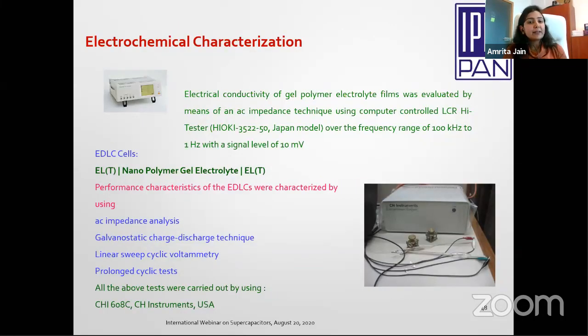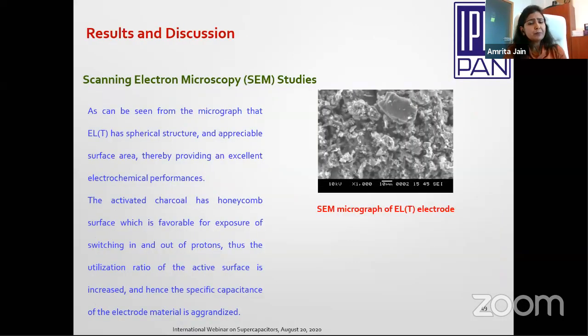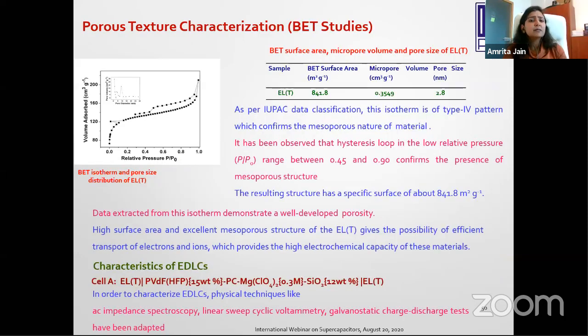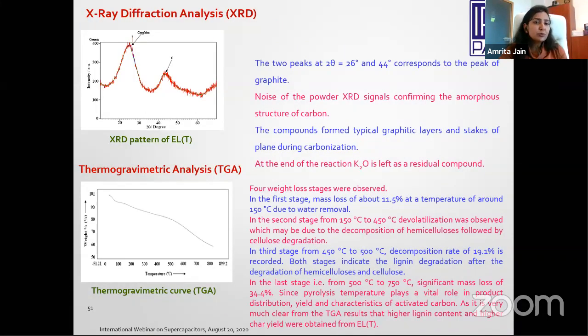So this is the electrochemical characterization. This is the device which I have used in India. This work was carried out in India. So this was the device which I used to carry out my electrochemical measurements. For cell characterization, a few standard techniques like impedance analysis, charge discharge technique, and linear sweep voltammetry have been used. Now these are the SEM results. This is the BET study, and remarkably, as you can see, I have achieved 841 square meters per gram of surface area. A few XRD results, I'm not going into details.